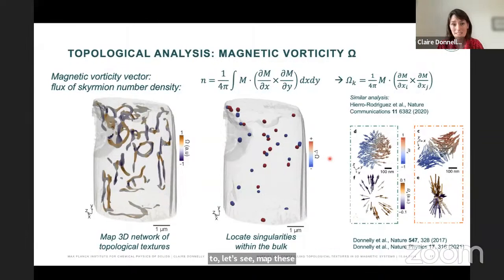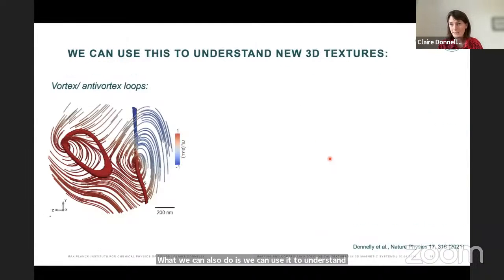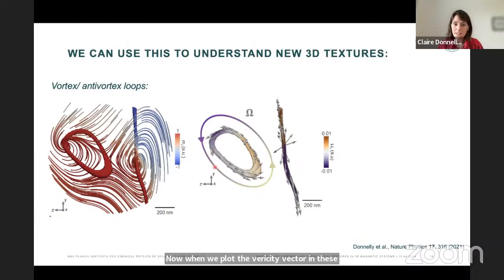Now, as well as using this vorticity vector in order to map these configurations, what we can also do is use it to understand particular configurations that we observe. And there are 2 textures that I want to introduce to you now. First of all, we want to look at these loops that we observed occurring in the magnetization that consist of vortices and anti-vortices, cores of vortices and anti-vortices within the bulk of our system. Now, when we plot the vorticity vector in these loops, we see actually that the vorticity vector circulates around this loop, meaning that we essentially have magnetic vortex rings.